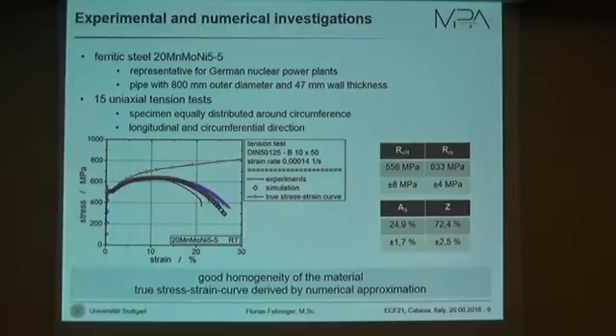To describe the homogeneity of the material, we did 15 uniaxial tension tests. We distributed the specimens around the circumference, and we took specimens in longitudinal and circumferential direction. As you can see, we have a quite good homogeneity of the material, which is kind of important for our concept. We also used those tension test results to derive our true stress strain curve, which we also need for the Rousselier model simulation.